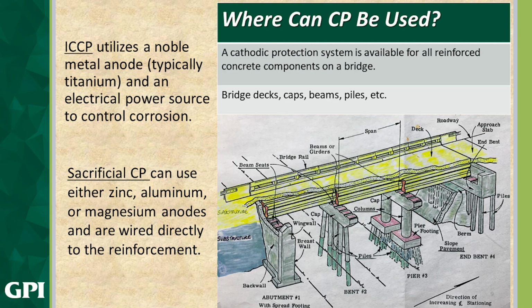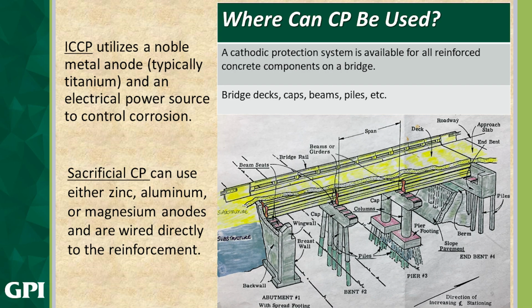Where can CP be used? Well, cathodic protection systems are available for all reinforced concrete components on a bridge. If you've got a reinforced concrete component, CP is a candidate. That includes bridge decks, caps, beams, piles, etc. ICCP, impressed current, utilizes a noble metal anode, typically titanium, and an electrical power source to control corrosion.